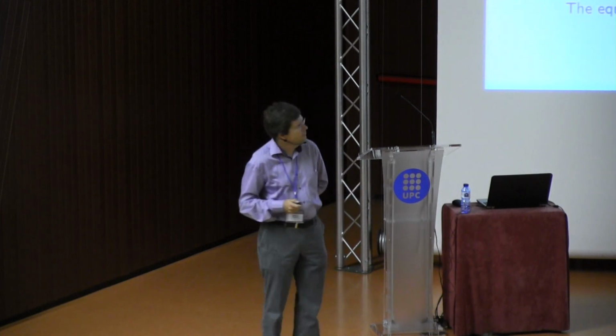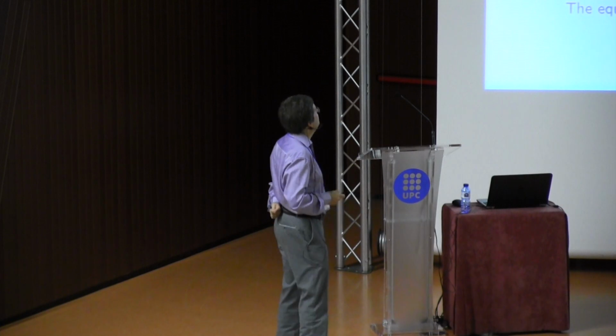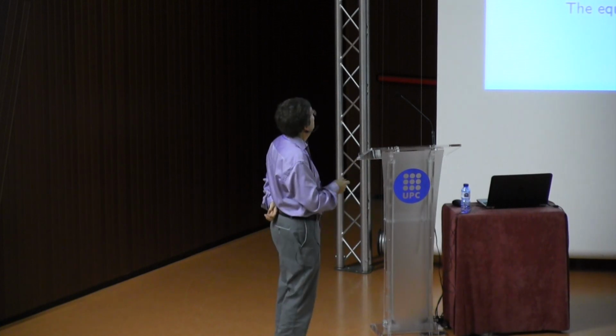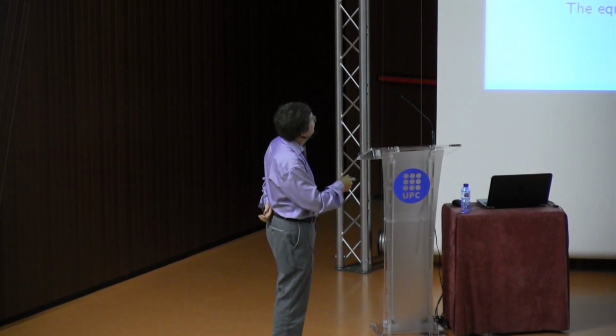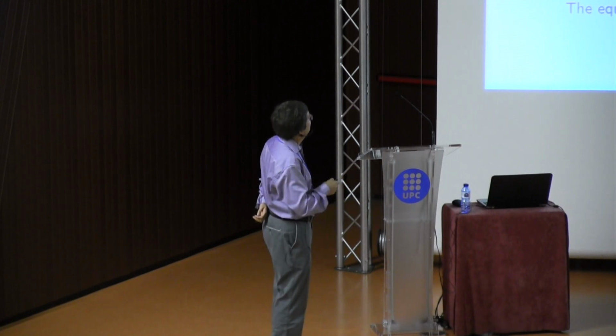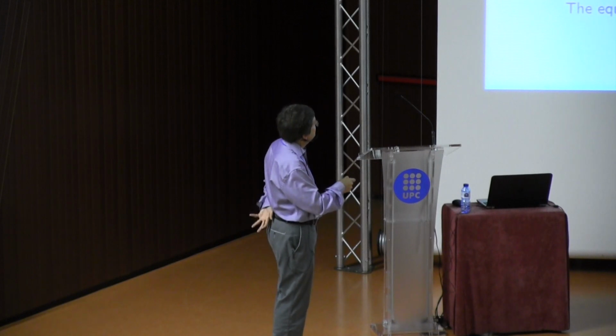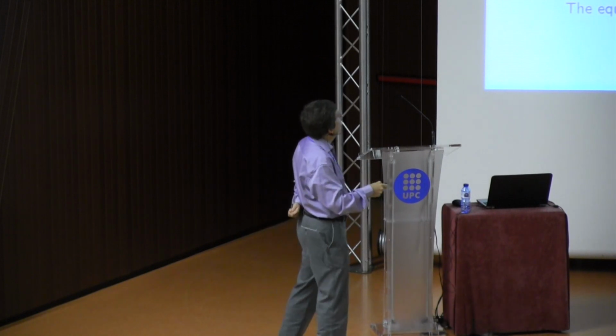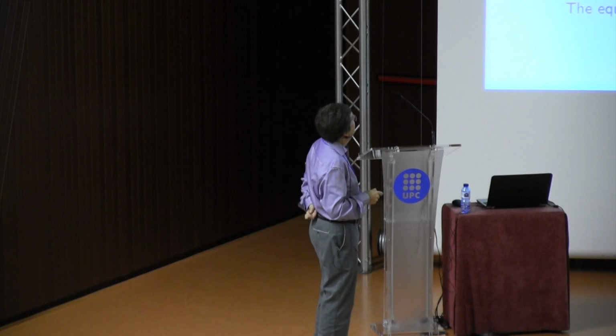Okay, let's give an example, plasticity. So strain gradient plasticity, how do you get it from this? You take a yield function with some equivalent stress. You look at the radius of the plasticity locus, and you have new hardening law.